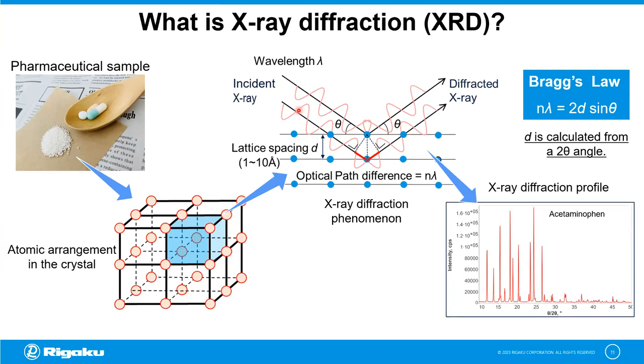You do not need to have a coherent X-ray beam. You just need to have a single photon or a wavefront. You satisfy Bragg's law when the path length difference is equal to a wavelength or multiple wavelengths, as shown here in this drawing.